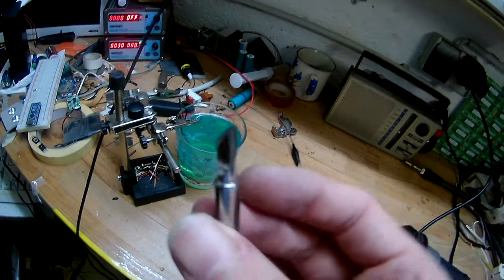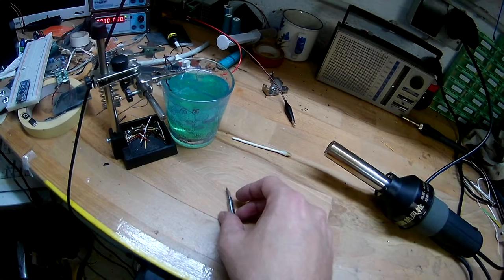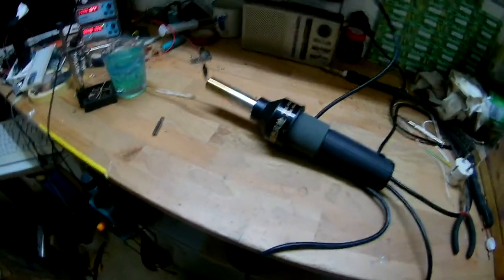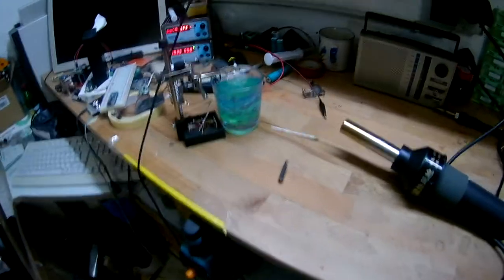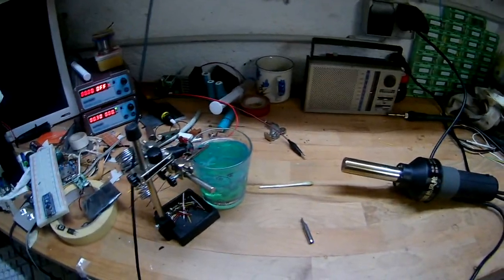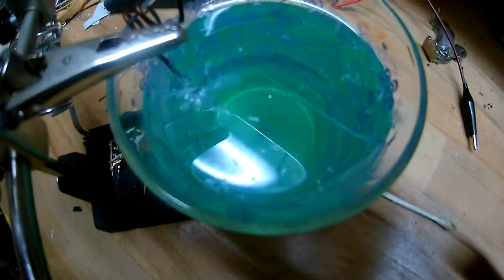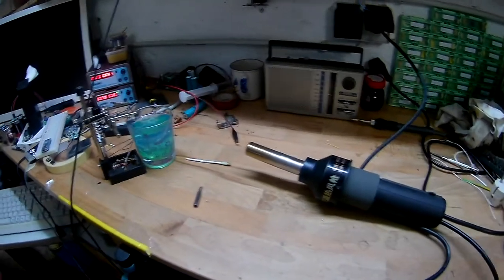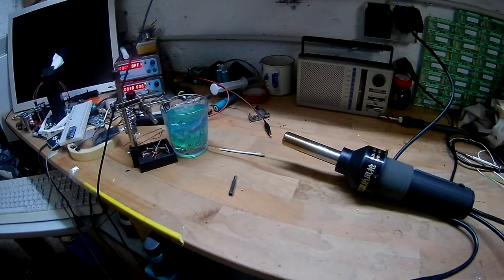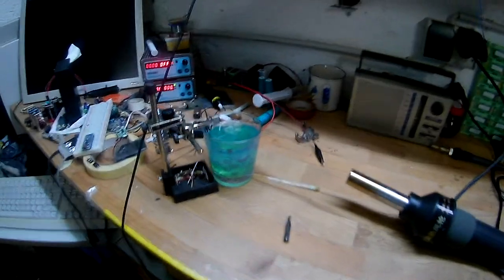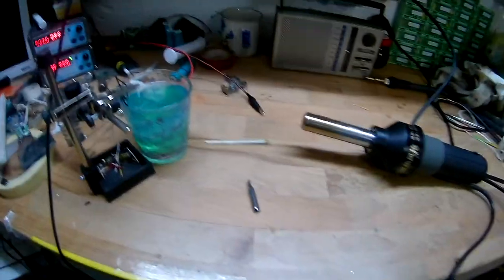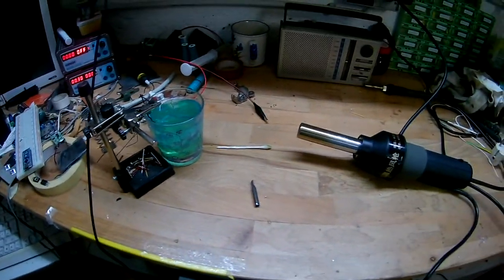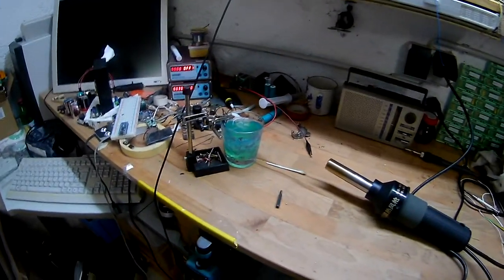But that was like, well, it took me a while to get that. And the reason for that is, well, you see the voltage here, 0.3 of a volt. I first tried it with I think two volts, it turned black. Then I tried it with five volts, turned black. 20 volts, turned black immediately. The black stuff just fell off. And you can kind of see down there in the middle is a black spot which is the black stuff that came off of it. So every time I put it into the thing, even with just one milliamp or even less, it just turned black, which is bad. So I googled a bit and it turns out that it's not the amperage that's important, it's the voltage.